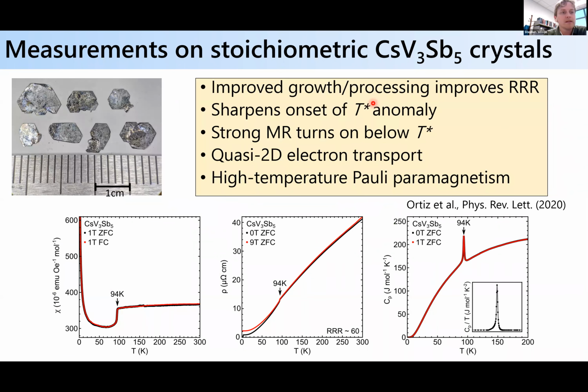One thing Brenda did was he then really perfected making stoichiometric single crystals of these materials. He developed an improved growth and processing technique, and as he did so, he improved the residual resistivity ratio. You can get it up to something like 60 to 80, around 60 I think typically. And now this is data collected on a single crystal where we can look at the susceptibility as a function of temperature.